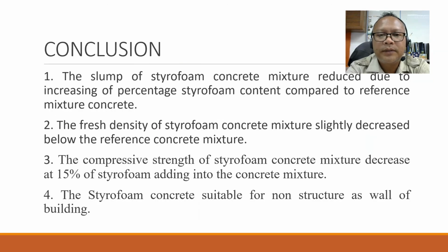For the conclusion, the slump of the styrofoam concrete mixture reduced due to increasing percentage of styrofoam content compared to the reference mixture concrete. Second, the fresh density of the styrofoam concrete mixture slightly decreased below the reference concrete mixture. And third, the compressive strength of the styrofoam concrete mixture decreased at 15% of styrofoam added into the concrete mixture. And lastly, the styrofoam concrete is suitable for non-structural use, such as walls of buildings.